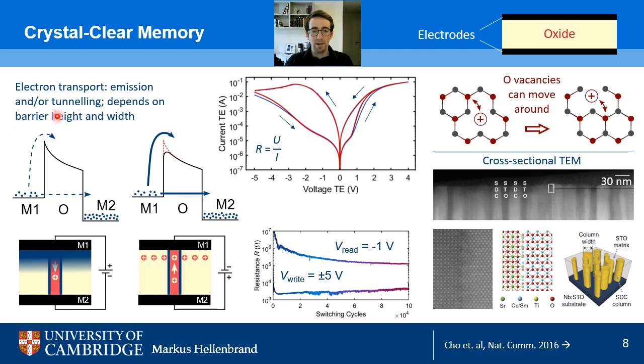Now, for a computer to operate, this has to be reversible very many times. So we have to be able to move the oxygen vacancies back and forth throughout the materials millions and billions of times in order to get a reliable memory for a computer. And initial measurements that I carried out are illustrated in this figure down here. So you see the number of cycles where we move the oxygen vacancies back and forth from the interface. And as a function of that, the resistance, that means the measured current, so the height of the barrier effectively. And we see that we can repeat this here at least 10,000 times. Then it took too much time to measure it even further, but it looks like the states are very stable. So by switching back and forth, we always get back to the same resistance in the high and the low resistance state. So this is very promising.